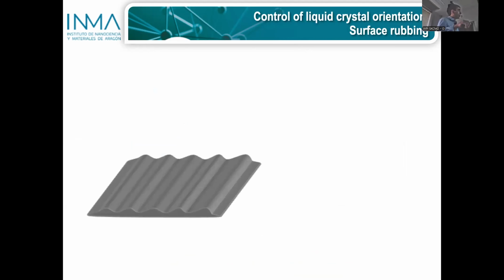Okay, going to how we get this orientation. This can be obtained by simply rubbing a very thin layer of polyimide coating on the glass. You wipe this with a velvet cloth in a linear fashion. Then you get grooves, you get orientation of the molecules.